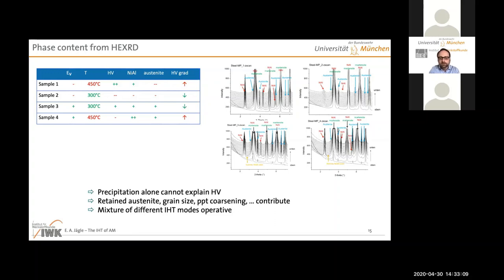And hopefully by the end of the year, you will be able to read a nice paper and we will have figured it all out. But what I can already say right now is that hardness is clearly not only correlated with the amount of NiAl phase. I'm just giving you qualitative data here, but very clearly, for example, in this sample down here, you have a lot of NiAl, but the hardness is rather low.